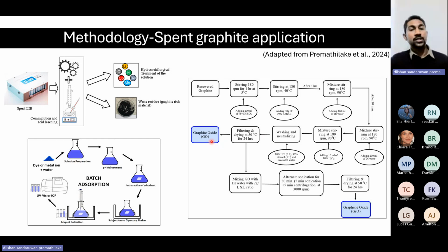To convert to graphite oxide, I use Hummers' method. It's a strong oxidation method where I use sulfuric acid and potassium permanganate along with deionized water. Once I created the graphite oxide, I converted some fraction of the graphite oxide into graphene oxide using the sonication method. The sonication fragments the graphite oxide, and some of the active sites attached to the graphite oxide will be lost. However, we'll see how they perform. Finally, both of these materials are used in the batch adsorption process for dye and metal ion contaminated water. I use spiked water samples to try out these two materials.